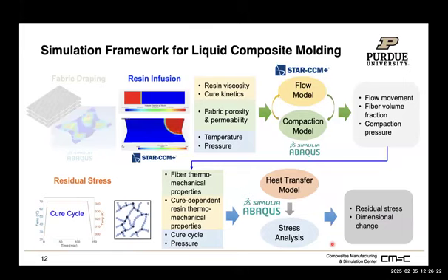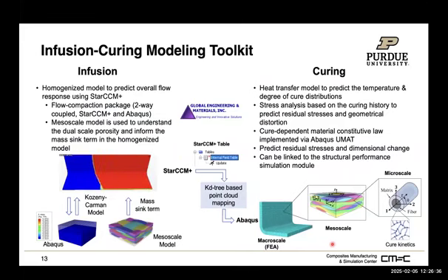Then once we know the draping process, we also need to see if there are ways to pass that information to the infusion and the curing. Over the years, we have also worked with a small company, Global Engineering Materials, to develop a smoother integration of the infusion and the curing simulation itself. For the infusion simulation, we need to incorporate the architecture of the textile and the flow compaction phenomenon, and leverage an external database so that we can pass information from the infusion, which is carried out by CFD simulations, to the FEA simulation. That way we can do the residual stress analysis on the part and predict the dimensional change and the stress distribution at the end of the manufacturing cycle.